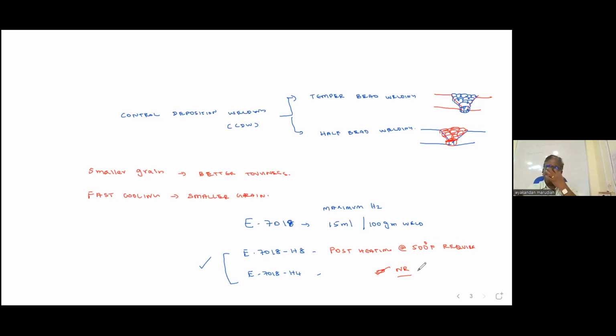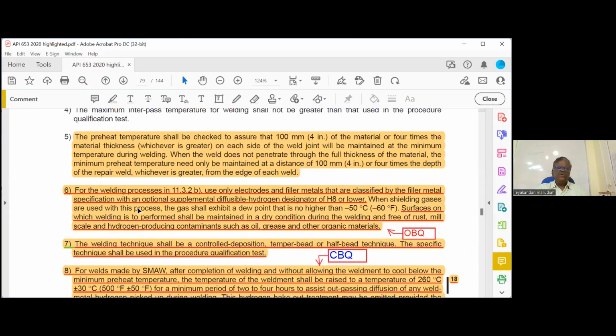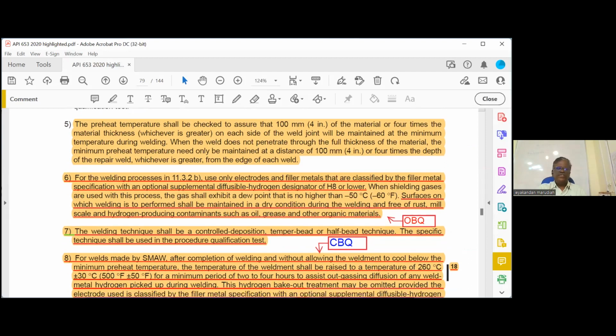The PWHT exemption only we are using, so there is no PWHT. Post heating means immediately after welding, for 2 hours you will heat it so that entrapped hydrogen will come out. That is not required for H4. Okay. In this area, very few questions. Highlight this one. Item 6: for welding, only use low hydrogen filler metals classified in the specification with an optional supplemental designator of H8 or lower. Then this is open to question. Item 6, last line: surfaces on which welding is performed shall be maintained in a dry condition during welding and free from rust, mill scale, and hydrogen-producing contaminants such as oil, grease, and other organic materials.